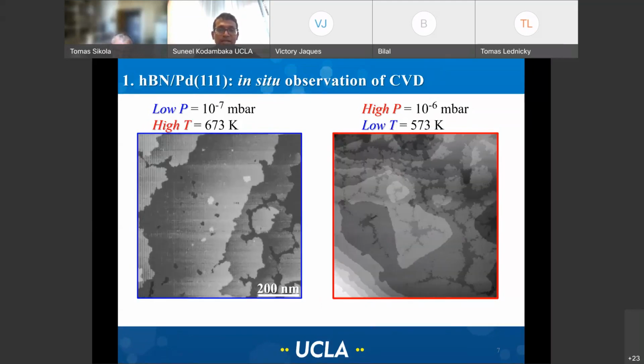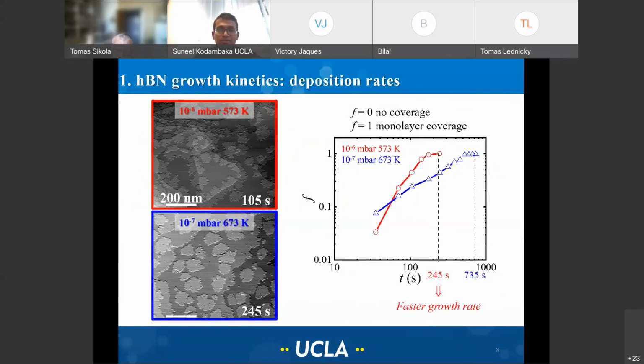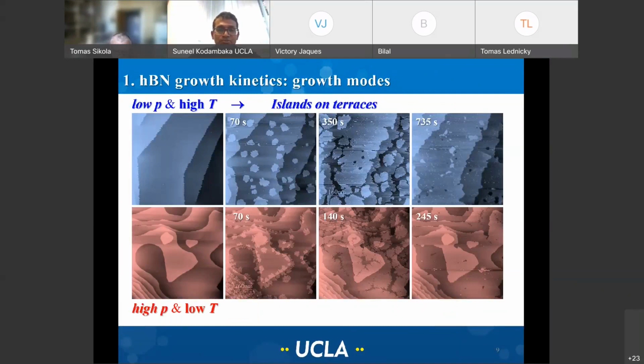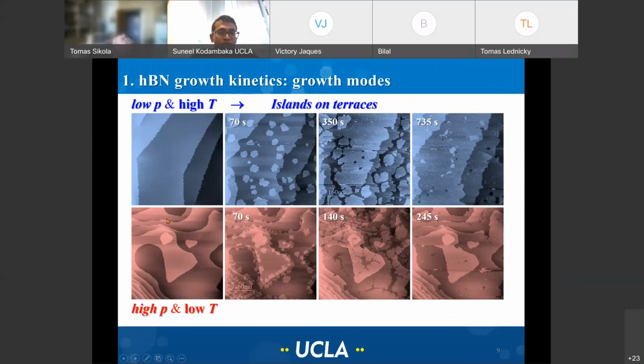Let me show it to you in the snapshots. And again, we can measure the growth rates, and I won't go through these details, but this is visually striking. So let me show it to you. We start with bare palladium, and we end up with a complete monolayer of boron nitride. But if you look at the differences in the way the boron nitride forms, here you see island formation on the terraces, followed by complete layer growth. And here you also get islands, but these islands are more fractal, and the attachment occurs preferentially at the step edges. What is more unusual is that the attachment occurs at the up steps, not at the down steps. So this is fairly unconventional growth.